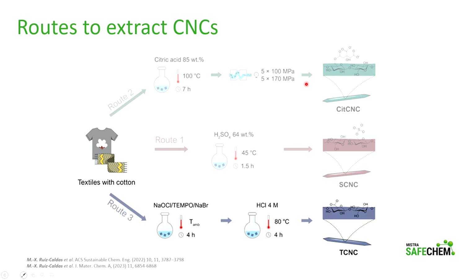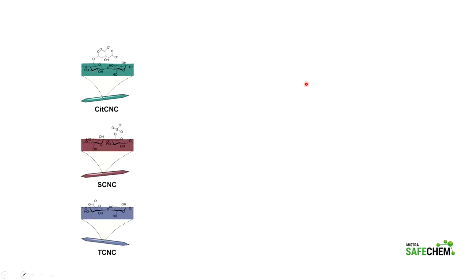And then we actually try another route that would allow us to also use a strong oxidizing agent in order to have particles with a lower percentage of impurities. So then these 3 types of nanoparticles are the ones that I firstly extract from textiles. It's important to point out that we didn't do any cleaning or anything. We just took as received textiles, and then we just processed them as I previously explained before.